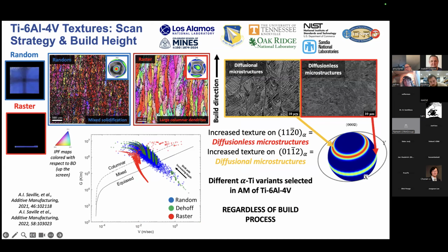My student Alec did a lot of work looking at the textures developed in the as-built condition and these diffusional and diffusionless kinds of microstructures. He showed that different texture components actually tell you a lot about what type of microstructure you've generated. And why we think this is important is that you can do a build, go and assess the texture, and have a really good idea, all the way back up to the high temperature condition, what the microstructure was like during solidification.